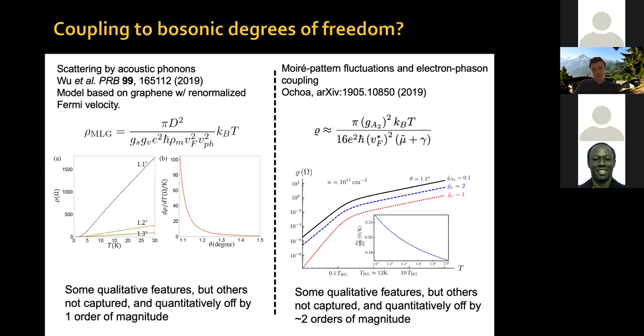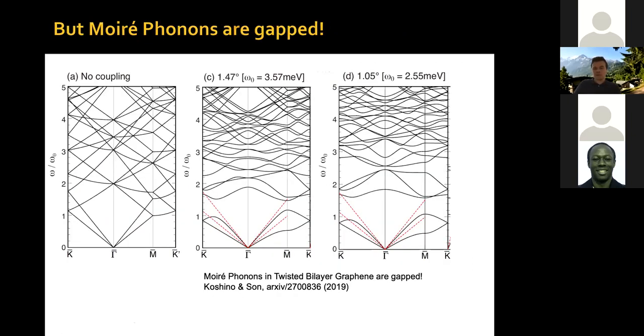Now, some people have argued that this linear temperature behavior of the resistivity could be due to various types of phonons, basically acoustic phonons in some cases, in other cases Moiré pattern fluctuations, which are also another type of phonons. But although the formulas can capture qualitatively some features, they mostly seem to be off by between 1 and 3 orders of magnitude, okay? And these are relatively simple models. As people make more and more advanced calculations, with more theoretical models, which include Moiré phonons, which actually happen to be gapped, etc.